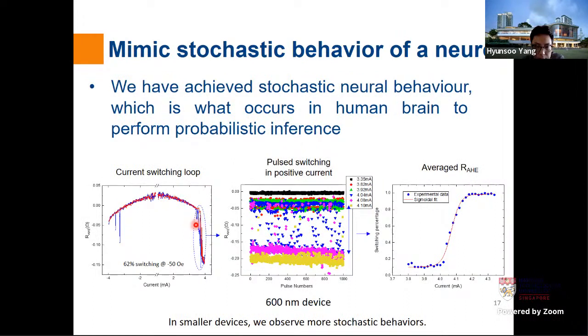And if you look at this switching part here with the higher current, you can see the data is not very smooth. Once we magnify those parts, you can see lots of fluctuation happen, and that also depends on the injected current level. If we apply, for example, 3.35, you can see the black data points, basically no change because the current level is not enough to switch.